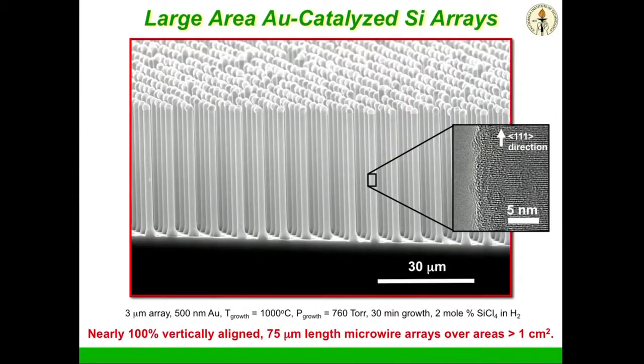If there's too little, it's going to pool up into little spots and grow filaments. If there's too much, it's going to drip down the sides like wax over the side of a candle, and we're going to grow more branched filaments that way. But if we match the surface tension just right, there's nowhere for it to go and the drops will stay. And then when we feed this a cheap precursor, silicon tetrachloride, this is what we get. These are single crystals by transmission electron microscopy of silicon growing along the 1-1-1 growth direction. They're 100% vertically oriented. Our initial scale up was, this is 1 centimeter.